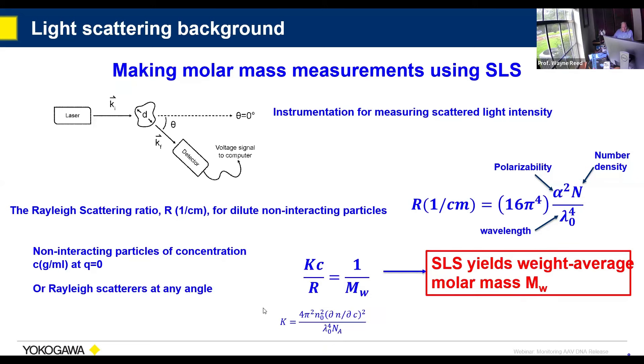Under the right conditions, you measure the Rayleigh ratio, knowing the concentration of your scattering solution in grams per centimeter cubed, along with an auxiliary constant that involves the solvent index of refraction, wavelength dependence, and Avogadro's number. The only real auxiliary parameter that needs to be determined is the so-called dn/dc — the optical contrast of the scatterer with whatever solution it's in. That's measured independently and is always the same. From this, you get the weight-average molar mass.